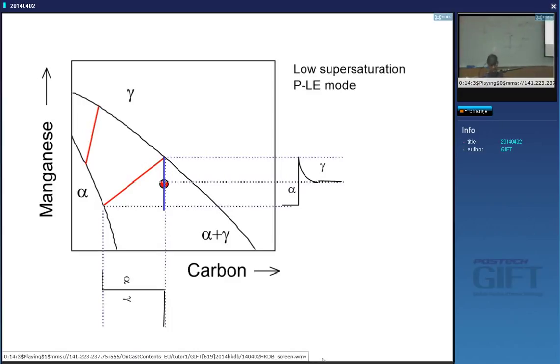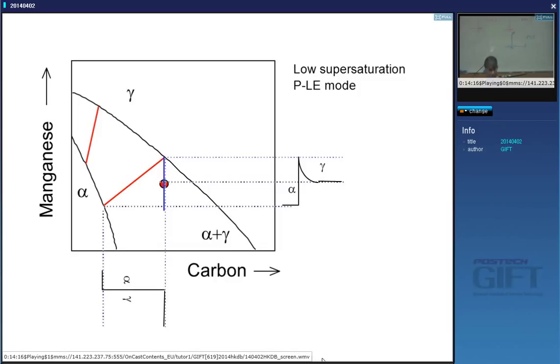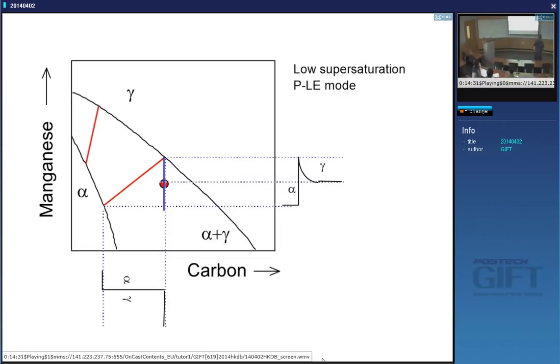You can see that the profile of carbon is flat, compensating for its large diffusion coefficient. But manganese must diffuse because the composition of the ferrite is quite different from C-bar, so there is long-range diffusion of manganese. This is what we call partitioning local equilibrium — the manganese has to partition, but we have local equilibrium because the composition at the interface is defined by the phase diagram. In this way, the ferrite can grow and the flux of manganese can keep up with the dramatically reduced flux of carbon.